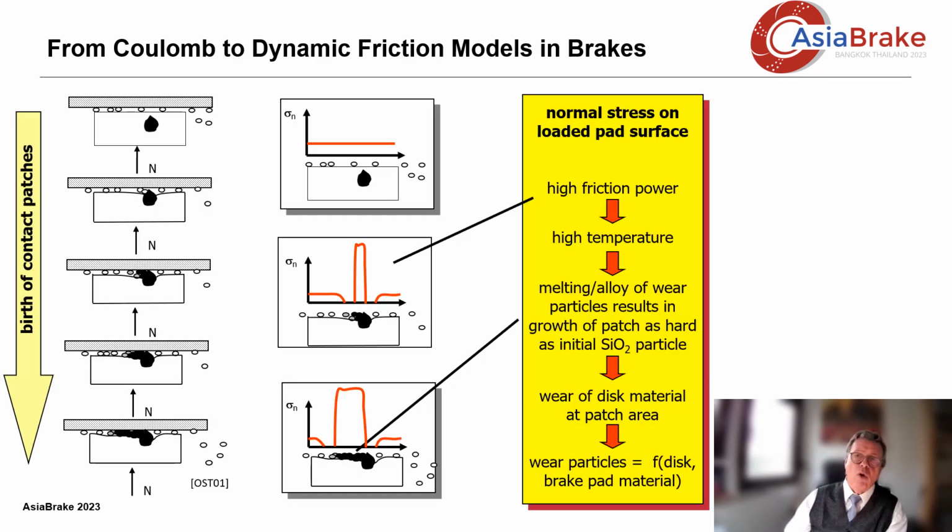First, the polymer matrix is rubbed off by the disc until the much harder stone particle reaches the surface. This particle has a much greater wear resistance than the surrounding matrix. With the wear on the polymer matrix, the particle is pushed more and more out of the matrix. With the sand particle, the normal force increases, and with it, the frictional force and the temperature.